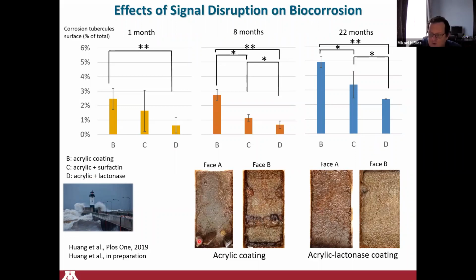Here you have the visual for it. So this is the sample B here. This is the control after 22 months. You have even fouling here. You can even see a few mussels there. And on Face B, you see more corrosion because we actually scratched that surface to accelerate corrosion. And on Face A of the enzyme here after 22 months, you see very little fouling and very little corrosion despite the scratching on the coating that has been done. So we're very, very impressed by the performance and even the durability of this.